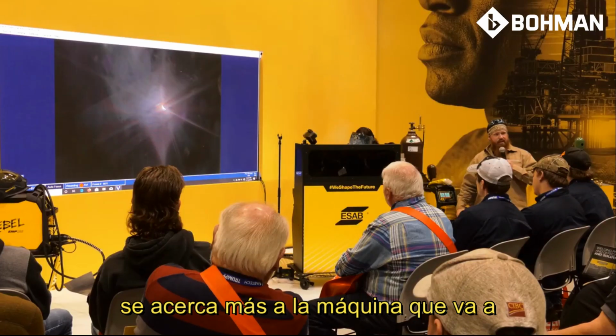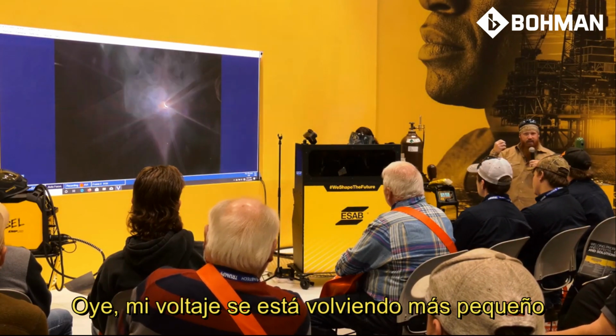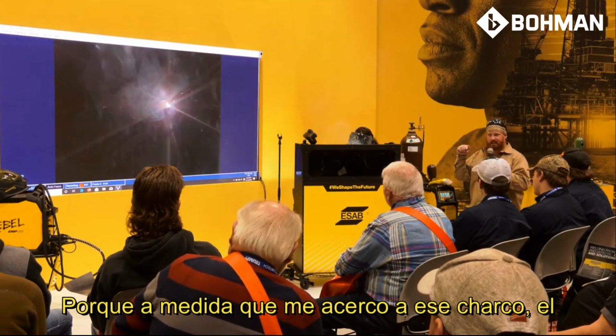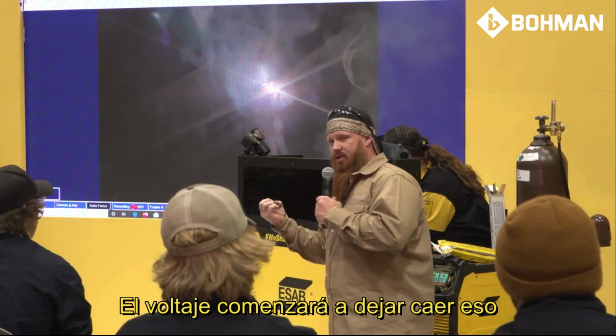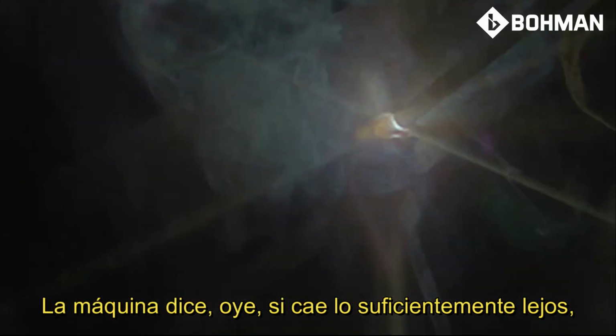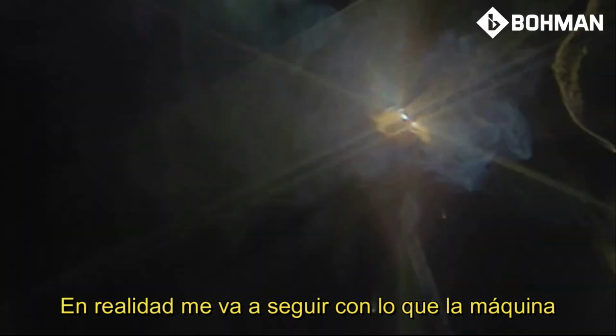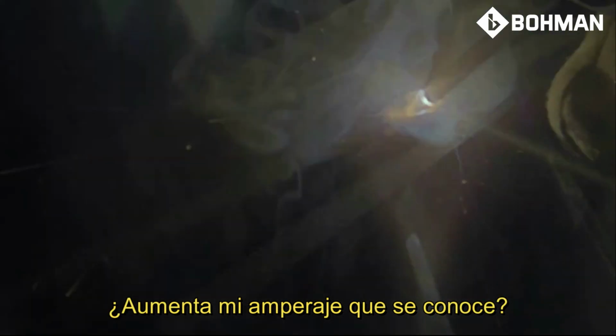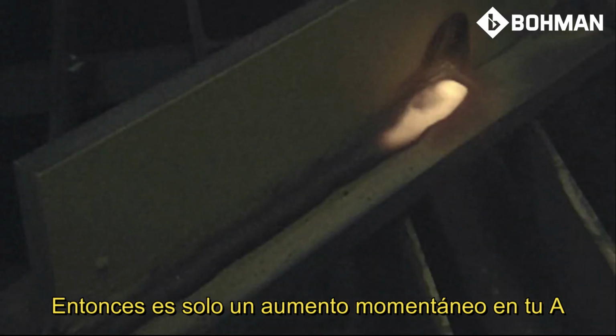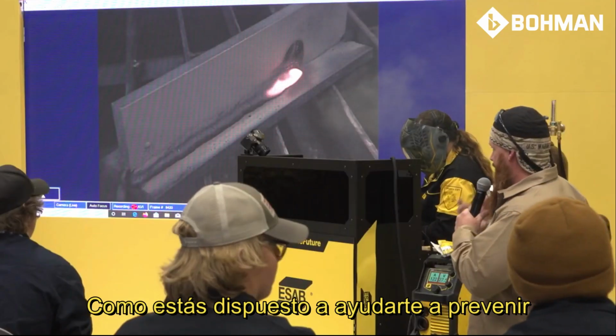Now arc force does the same thing. As that puddle gets closer, the machine's going to understand, hey, my voltage is getting smaller, because as I get closer to that puddle, the voltage is going to start to drop. The machine says, if it drops far enough, it's actually going to stick. So what the machine does internally is increase my amperage by that known percentage to give me a hotter puddle. It's just a momentary increase in your amperage as you're welding to help you prevent sticking.